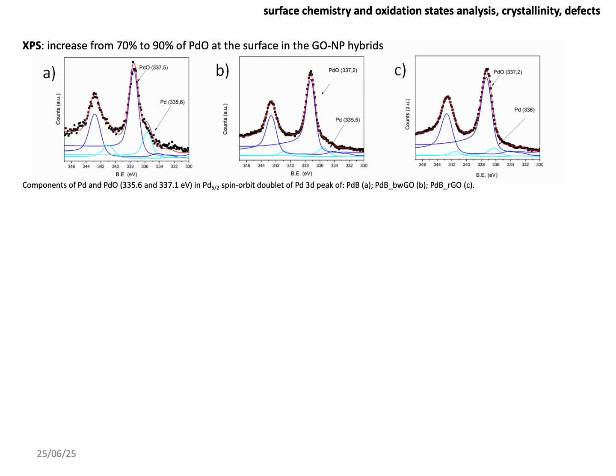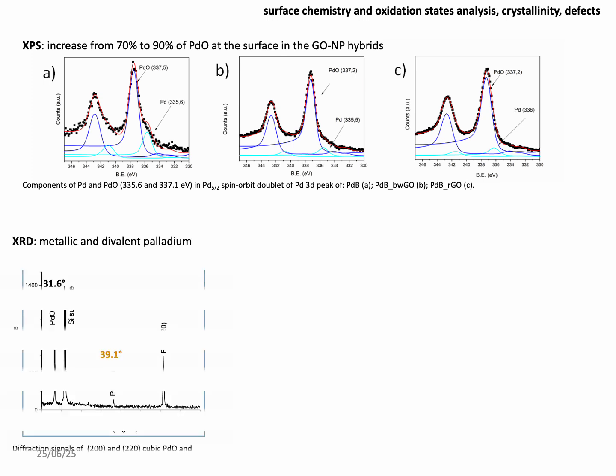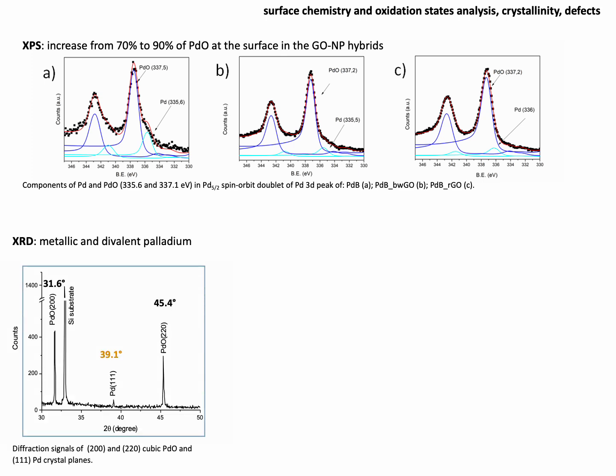The XPS analysis revealed that the palladium 3d spectrum includes both metallic and oxidized palladium, with the peaks at 335.6 and 337.1 electron volts from the deconvolution of the 3d 5/2 component. The surface is about 70% palladium oxide, which increased to 90% in the hybrids, which indicates more oxidation, and XRD confirms, showing peaks at 31.6 and 45.4 for the palladium oxide planes 200 and 220, and also the peak at 39.1 degrees for the metallic palladium 111 crystal plane.